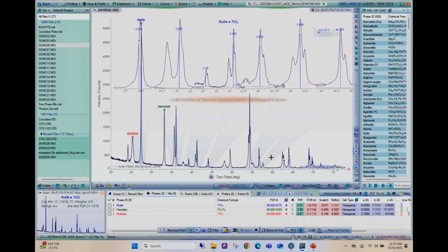Everybody has a different mathematical equation for their figure of merit. This one, goodness of match, which was in PDF5 Plus, a perfect match is 8,000. It looks at 8 peaks. Most may look at 3 peaks or maybe a whole pattern. And how does a pattern match? In this particular case, the smaller the figure of merit, the better your match. Okay, you just need to know what's there. So in this case,